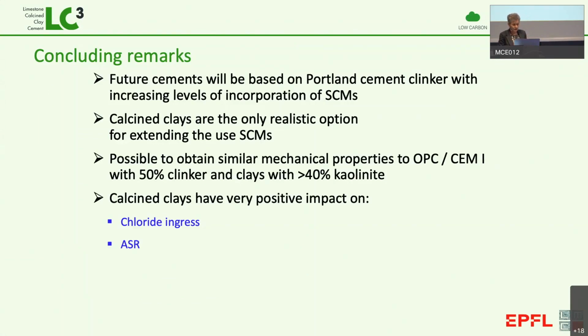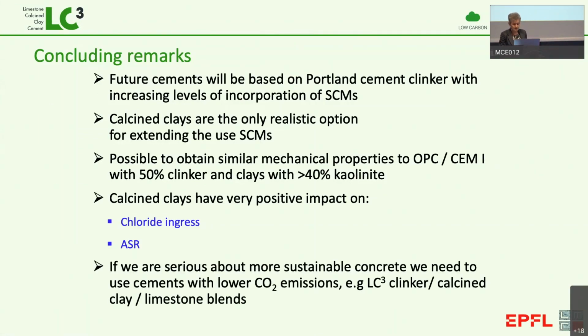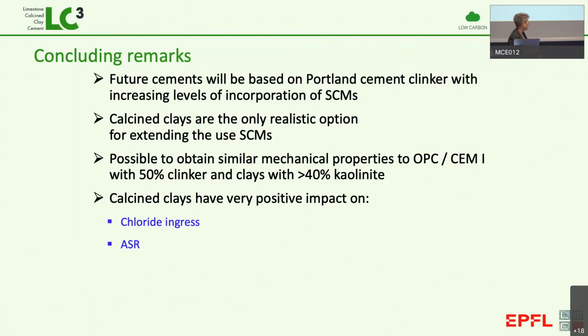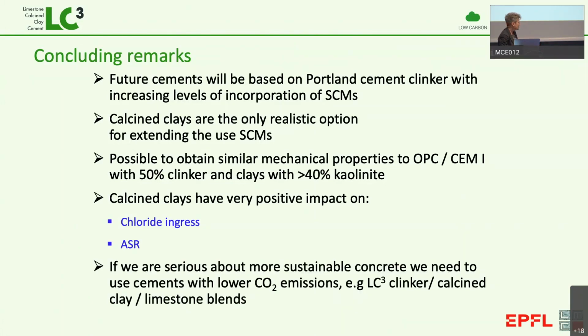And these can have advantages, particularly in terms of certain durability issues like chloride ingress, which is the number one problem, and alkali silica reaction, which, for example, is affecting about 20% of our dams here in Switzerland. So I think this LC3 has a very serious role to play in lowering the CO2 emissions of cement and concrete.